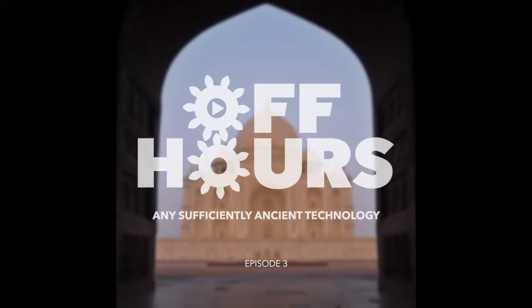And I should mention that one of the reasons why I started casting my own work is that it is challenging, and it needs different temperatures of the flask and different temperatures of the metal to cast properly. They're outside of the norms of what most jewelry casting houses use. While they're certainly capable of casting them, it would be very difficult to put my work into the same flask as, let's say, some standard wedding rings or engagement rings, where they're much thinner and much smaller. You can't cast very heavy, thick objects in the same flask as something that's very light and very thin. They need different metal parameters when it comes to temperatures. So that's one of the reasons why I ended up casting my own work. It was difficult to find casting houses that were willing to do the extra work to cast just for me.